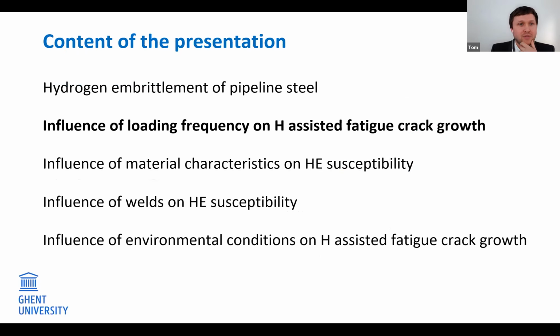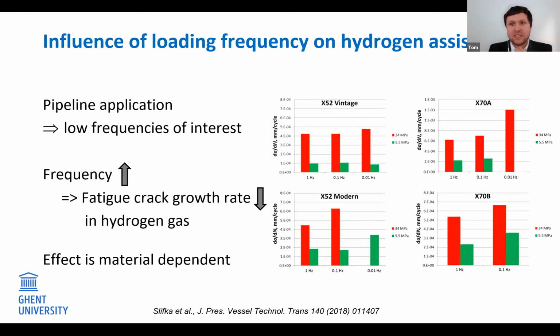Let's talk about different influences. First one is the frequency. Well, studies indicate a negative correlation between frequency and the fatigue crack growth rate in gaseous hydrogen atmosphere. Hydrogen embrittlement is time dependent, as hydrogen needs to absorb into a steel microstructure and can diffuse to the crack tip in order to deteriorate the material.